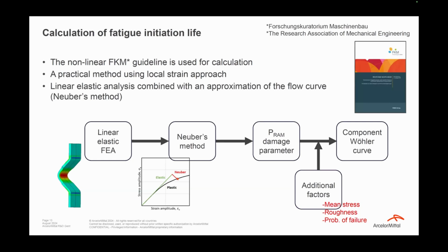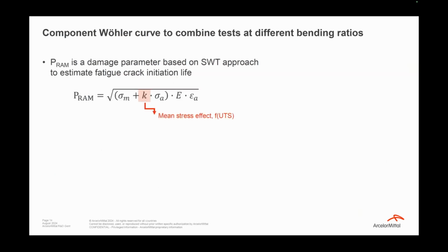And to calculate the fatigue initiation life, we are using the FKM guideline. This is an association in Germany. It's called the Research Institute for Mechanical Engineering. I'm not going to attempt to pronounce the German name, but it provides a practical method using local strain approach. What we do to come up with a component Wöhler curve is we do some linear elastic finite element simulation using Neuber method to approximate the plastic strains and stresses. Then we can calculate the damage parameter, add additional factors, and then come up with a curve that is specific to the component that we are considering.